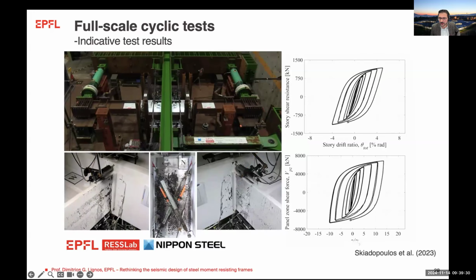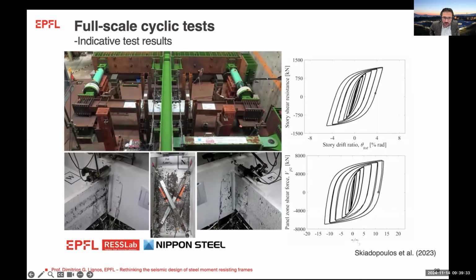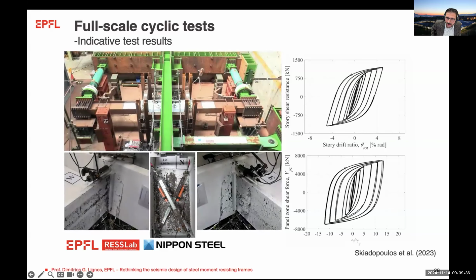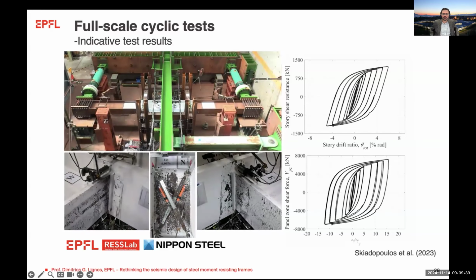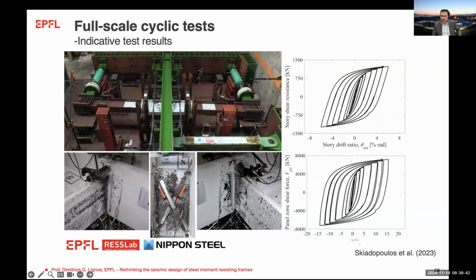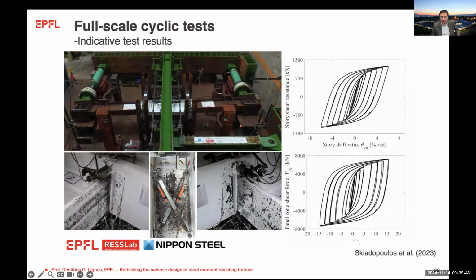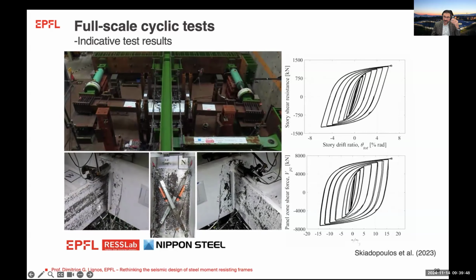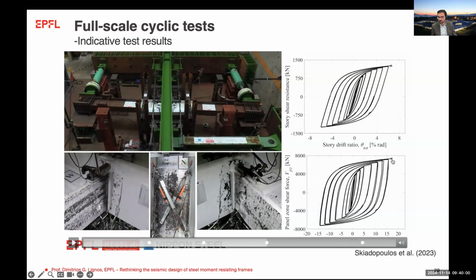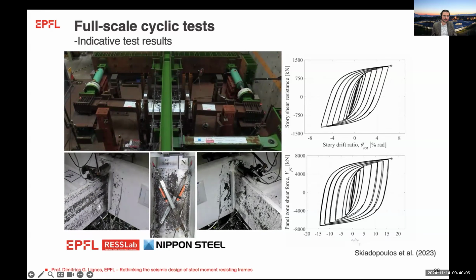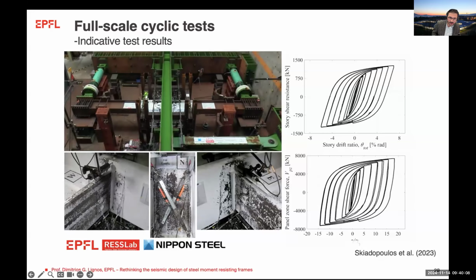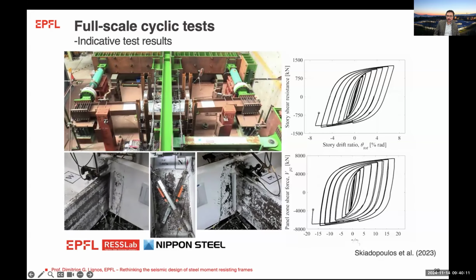Now, we kept testing this up to pretty much the equipment limitation. And what we saw is that, in fact, our objective to achieve stable behavior at very large drifts was actually met, which was quite interesting because that would mean that I have instability-free performance by leveraging shear yielding in the panel zone without exhibiting fracture as anticipated in these connections. And notice here that I am indeed above 15 gamma Y, and I'm already at a drift that is in the range of 6%.